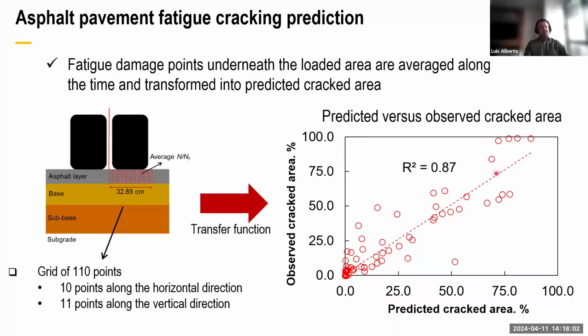So these are the national test sections. We have a very nice calibration, very nice predictions. Sometimes you have some points that look to be outliers, but actually, when you look in this space here, we're not taking into account the timing for this damage, time or number of repetitions. And for fatigue cracking, once the pavement starts to crack, the cracks grow really fast. So we need to take a look at this data.